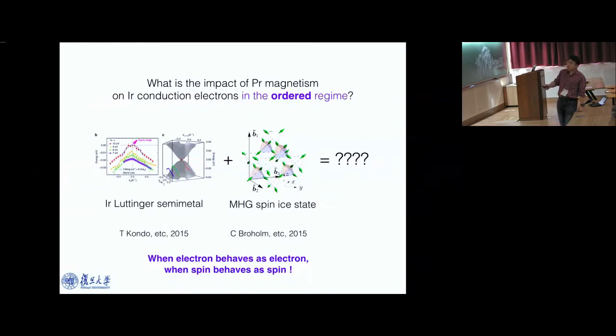So this is the example of 2 in 2 out spin-ice manifold order. So this has been observed by neutron diffraction. So neutron sees the local moment. So angle-resolved photoemission sees the band structure of conducting electron. So now we want to combine these two experimental results together and ask what's the consequence, right? We want to synthesize these two pieces of experimental information, from different experimental groups with different probes, and ask what's the consequence, right? This is really based on the experimental result and ask what's the next, right?